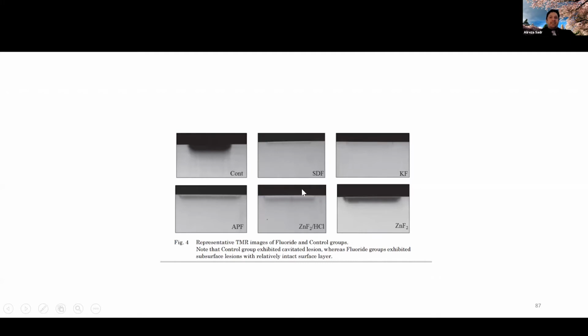And it's interesting that we didn't get as good effect with zinc. We got some effect, but we didn't get as much effect as silver diamine fluoride. Here is silver diamine fluoride applied over the dentin, and dentin exposed to caries challenge. Here's control if you didn't have any. This is a transverse microradiography technique, where you look at a very thin cross-section of dentin. And what we found was that SDF has an absolutely unbeatable root caries arresting and prevention effect when we compare it to the APF, zinc fluoride, or other types of fluoride.